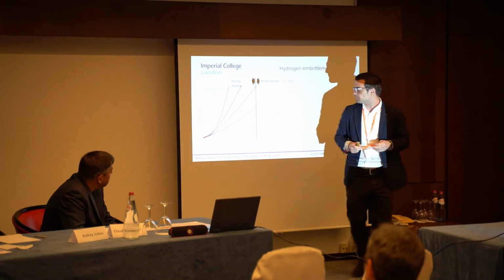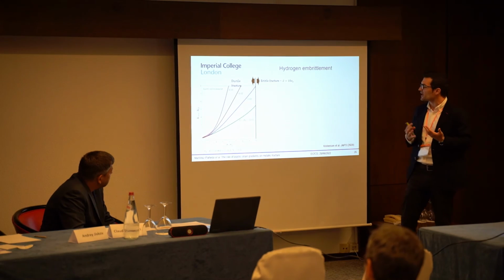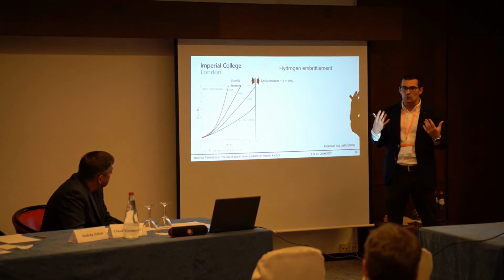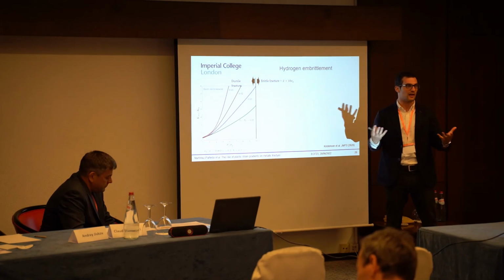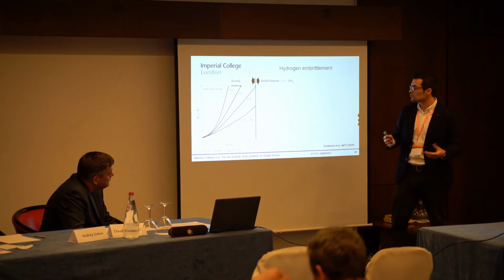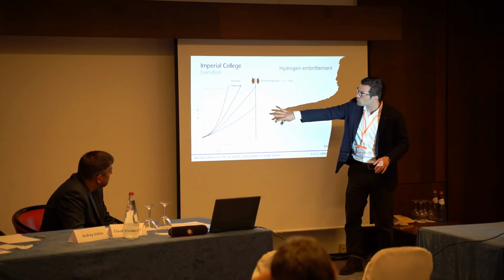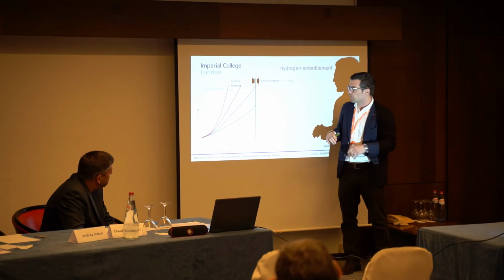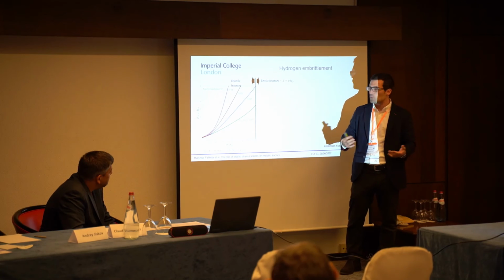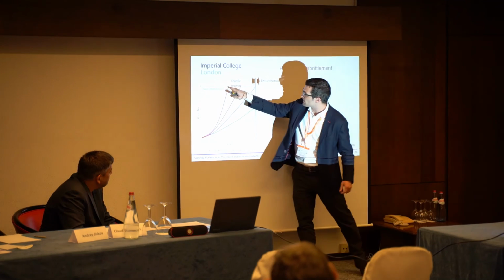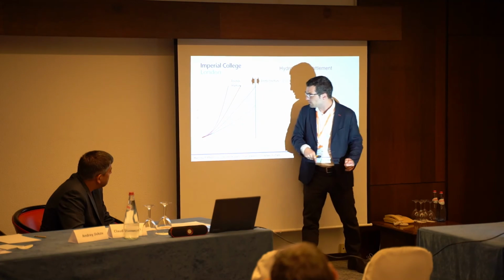And one last thing that I want to say about hydrogen embrittlement is that one thing hydrogen does is to reduce the fracture energy. And by reducing that fracture energy, you are changing the R0. So if I take you back to these steady state toughness curves that I showed you before, the same metal in the absence of hydrogen will have a very large fracture energy. It will fail in a very ductile fashion. So you are somewhere here in this regime. Your L to R0 ratio is very small.